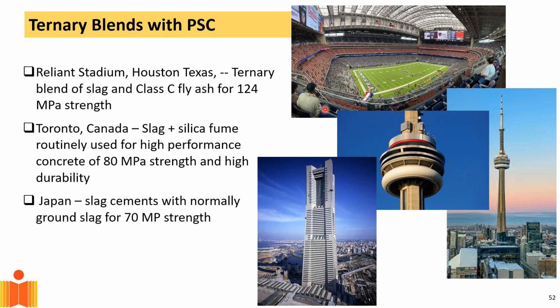Slag gives me a slightly higher reactivity. It gives me a slightly better chloride binding capacity, and it gives me better strength performance. And fly ash helps me with the rheology and long-term strength. So I can basically start combining these, and this is already in play. So we have ternary blends that have successfully been used. So you see that the Reliant Stadium in Houston, Texas, it was a ternary blend of slag and Class C fly ash, and they were targeting 124 megapascal strength.